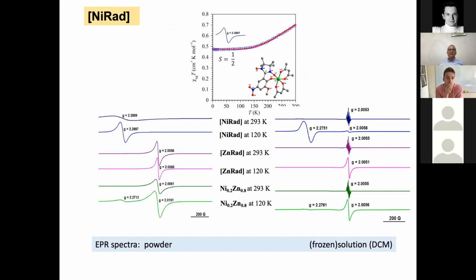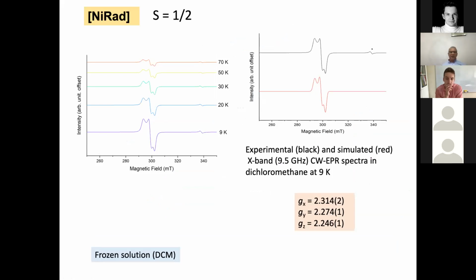More interesting for us is the nickel derivative, because we can observe below 120 Kelvin the signature of S = 1/2. These are the spectra recorded in solution or frozen solution and in powder. We observe the signature of the radical at room temperature, and at low temperature, both in powder and in frozen solution, we observe the signature of the S = 1/2 ground state. By decreasing the temperature in both X and Q bands, we observe the rhombic symmetry of the resulting ground state through the antiferromagnetic interaction between nickel and the radical.